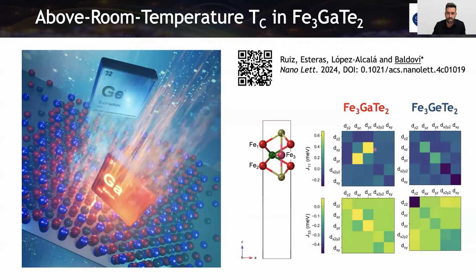Then we can go also to the mechanisms to see exactly which orbitals are responsible for that. In the case of the iron gallium tellurium, we have these ferromagnetic interactions, yellow here, that go from the DYZ orbital to the DXZ. These are the main interactions that are favoring this J that is now ferromagnetic. And it doesn't appear in the case of germanium. Germanium is not mediating this effect. And it has these antiferromagnetic interactions here that are stronger.